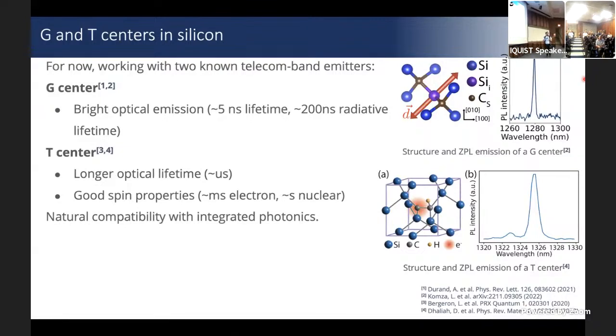This G center does not even have spin, so it's kind of boring in that regard, but it's a good optical emitter. So what do I mean by good? It has a short excited state lifetime, so it's a fast emitter. It has a radiative lifetime of about, we think, 200 nanoseconds or so. So we first started experiments with this system because it's a nice platform to start seeing whether we can do quantum optics in silicon photonics.